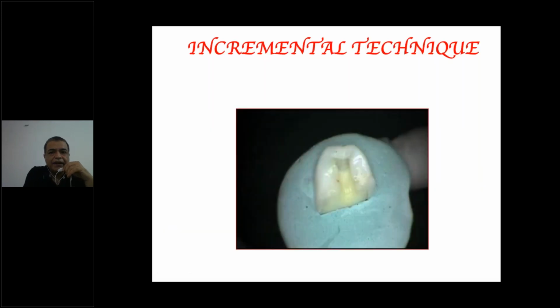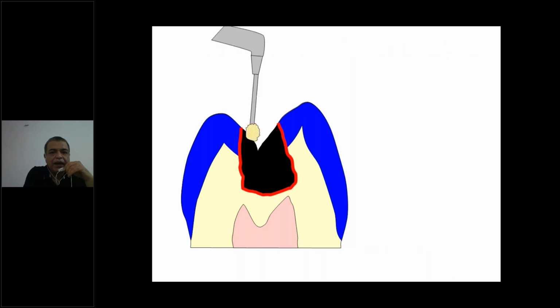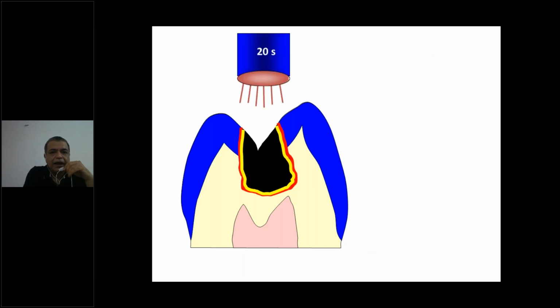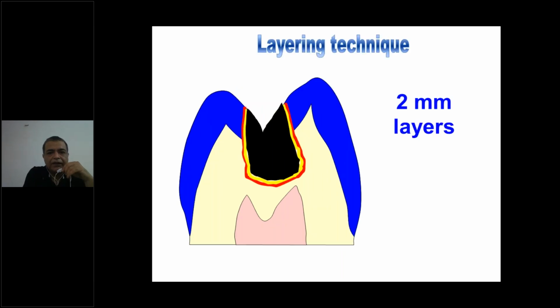So what is the incremental technique? Just imagine that this is a class 1 and you have done your bonding. Now you're going to restore it with composite. So you put a 2 millimeter layer of composite in oblique fashion. Now just imagine what is happening because of this oblique layering. First thing is I am putting a 2 millimeter layer so that I have a sufficient amount of curing. And by oblique layering, I am reducing my C factor.